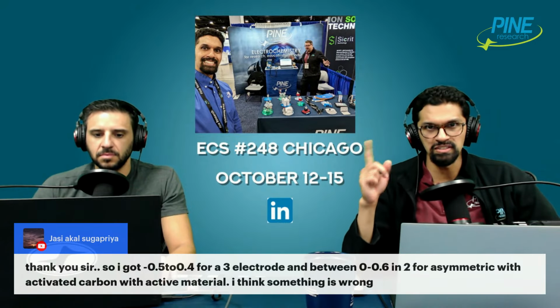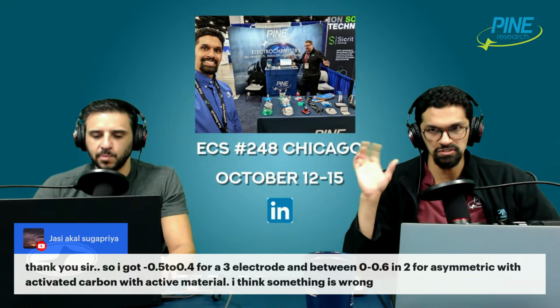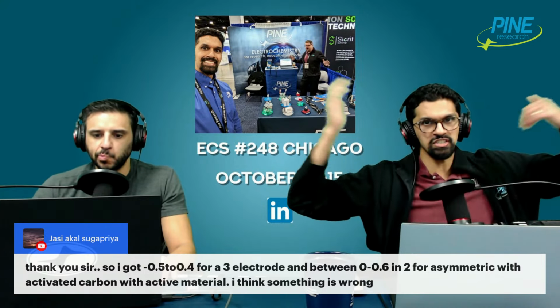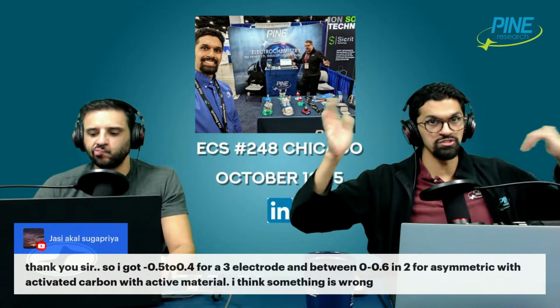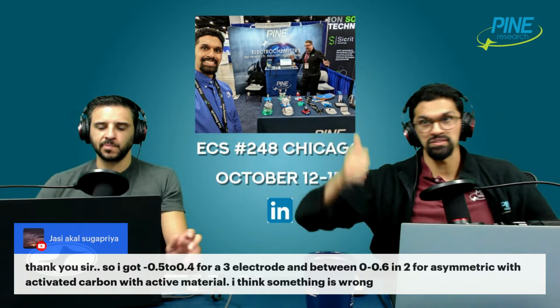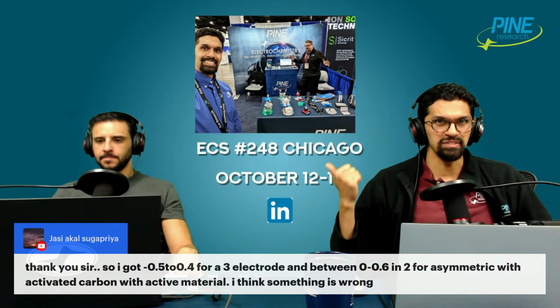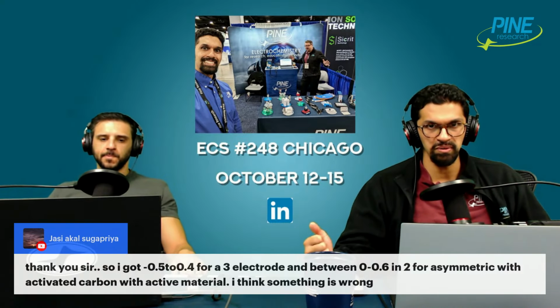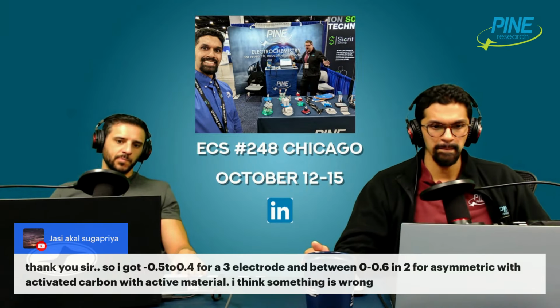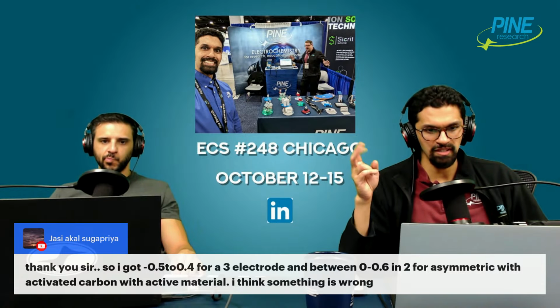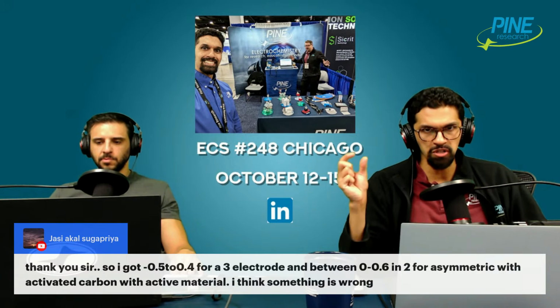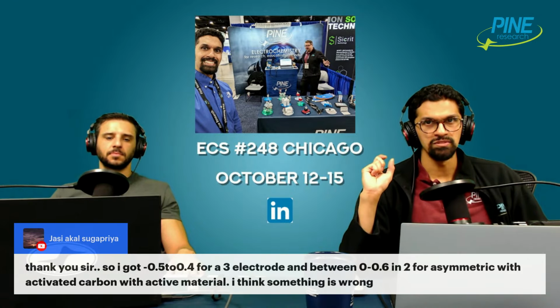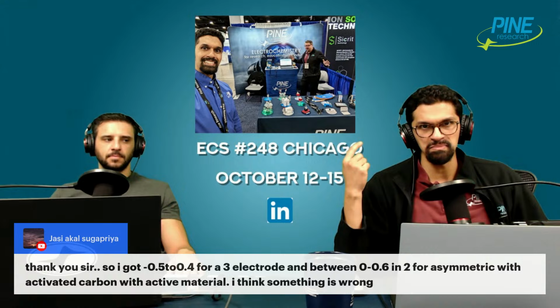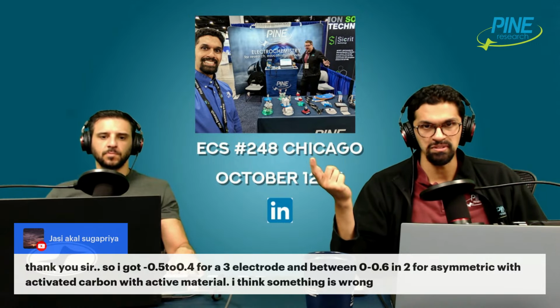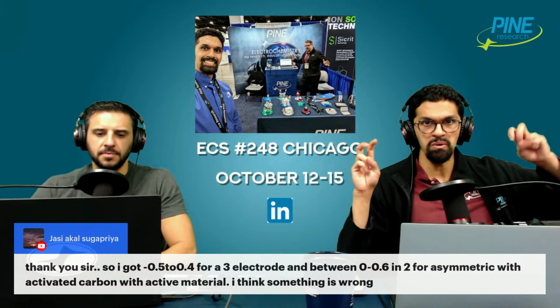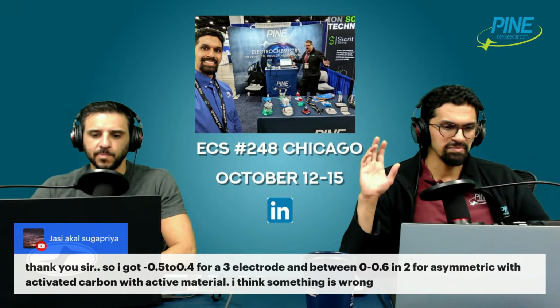So I think for a single electrode, and in a 3 electrode, because you're only looking at the working electrode, you're able to fully explore the voltage range, and the current is just due to reactions happening at the working electrode. The counter electrode has to balance the charge, but the counter electrode isn't governing what the current flow is. It's not like the driving force for it. But in the 2 electrode symmetric cell, I'm not too surprised that you have a smaller voltage range, because you're now at the mercy of what other things can be happening at the other electrode, because that's going to affect your current and what the quote effective voltage range will be. That's kind of my thinking.